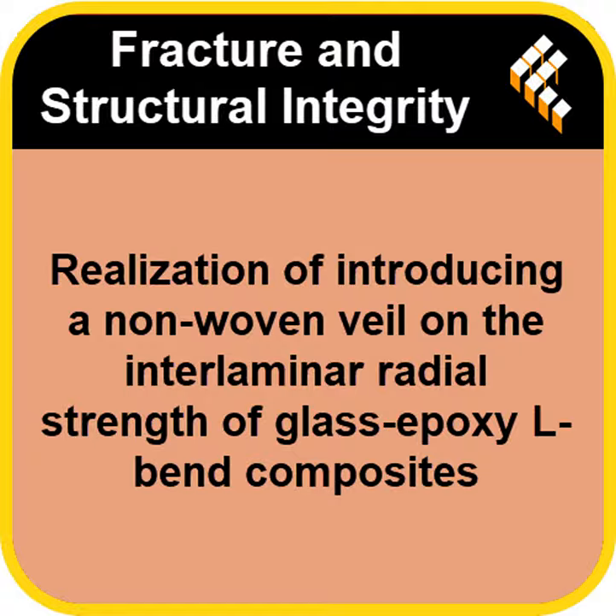They showed signs of trouble. You could see things like fiber traces, basically marks left where fibers had pulled out cleanly, suggesting poor bonding again, lots of matrix cracking. And maybe most tellingly, evidence of crushing. Crushing, like the material itself got pulverized. Yeah, localized crushing of both the fibers and the matrix. This points directly to those stress concentrations we talked about. The load wasn't distributed, it focused intensely in small areas because of that stiff, poorly bonded veil, leading to a sudden, brittle, almost explosive failure.